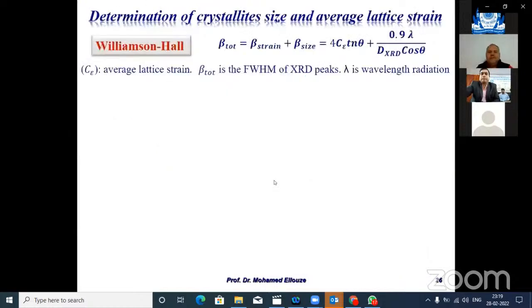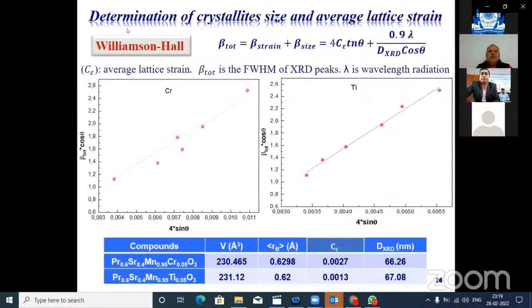From this part of X-ray diffraction, we can also calculate the crystalline size and the average lattice strain using the Williamson-Hall formula. Here we have obtained from X-ray powder diffraction that the crystalline size is about 66 or 67 nanometers for this kind of sample.